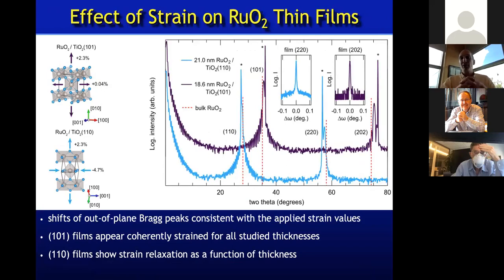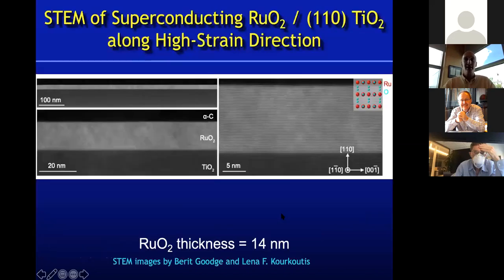A starting place is to look at X-ray diffraction and see, are these films commensurately strained, and do they behave like you expect them to? And indeed, if we look at the position of the out of plane peak compared to where it would be in bulk, for both strain states, things shift in the right direction. So here we're putting on mainly biaxial compression in the superconducting case of interest, which should elongate it in the out of plane direction, which it does. And in this case, we're putting it in biaxial tension, which should be the one that causes it to shorten out of plane. And you can see that the film peak is shifted to the right of the unstrained peak. So it behaves like it should in that sense.